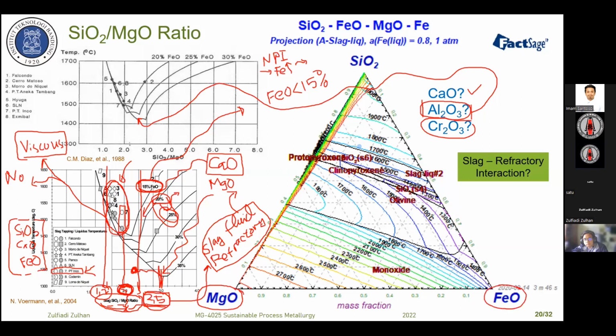And until today, if we talk about the slag for the electric furnace for a ferronickel plant, we just consider iron oxide, then MgO, and then SiO2, and we see at 1,600 Celsius degrees the whole slag is melted, or we can also take a lower temperature. We can also put here, for example, 1,500 Celsius degrees, the area where all the slag is melted, and then they plot their slag composition in this diagram, whether the slag is melted or not. For example, here we put the silica to magnesia ratio 1 and an iron oxide content around 10%. In that case, the melting point of the slag is not 1,500, it could be 1,550, in between 1,500 and 1,600.